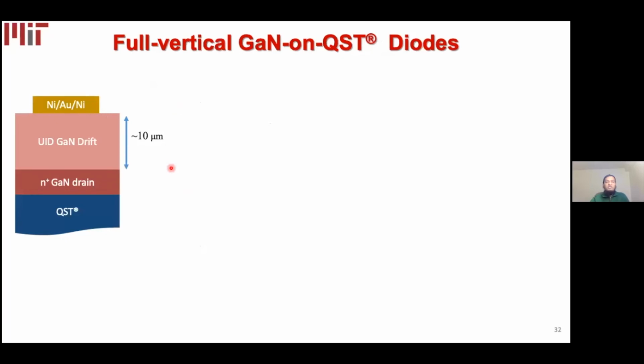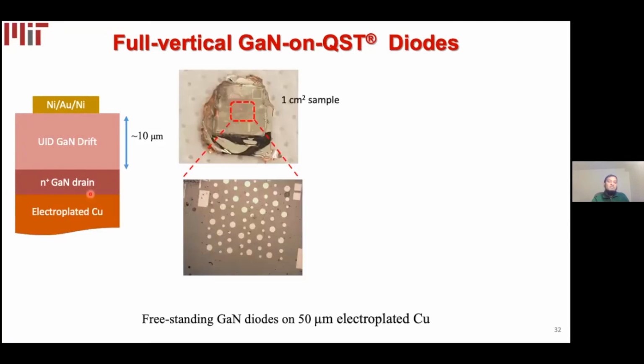Before going into the FinFET fabrication, we developed the process on a simpler structure, diode devices. The diode structure after fabrication and before substrate removal looks like the one I'm showing here on the left. We have a nickel gold nickel Schottky contact on the front side. Then we have the drift region, which is about 10 micron thick, the N+ GaN bottom layer, and a QST substrate. Once we remove everything and replace the substrate with electroplated copper, this is how one of our finished samples looks.